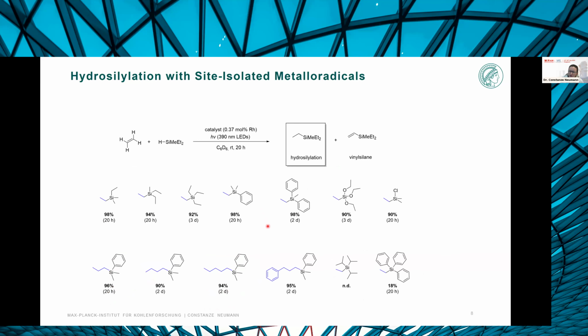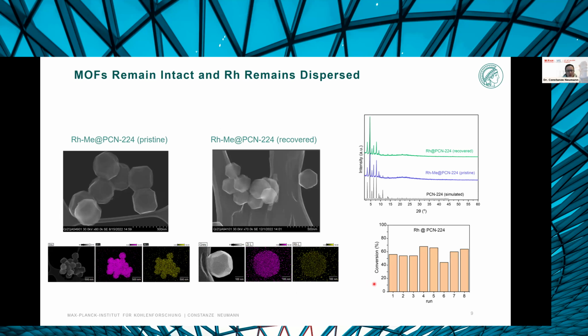And while to us the most interesting system was ethylene, because it does not have any radical stabilizing groups present in the molecule, and it's the most simple and unbiased system, due to the large pores that are present in PCN222 and 224, you can also use larger substrates, so different olefins are compatible, and you can also use different silanes. The reaction starts to fail, however, when the steric bulk around the silicon center becomes too large, in which case the rhodium no longer effectively interacts with it.